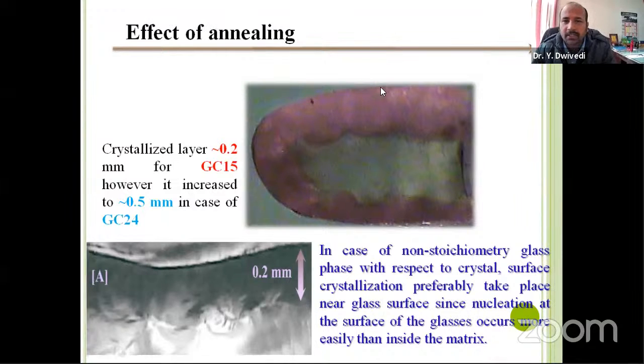You can see that due to some heterogeneity present near the surface and in the sample as well, crystallization starts from the surface and branches inside the system. So what happens is this unique structure forms: the upper layer is crystallized, you can see the pink scattered light, and here in between there is a transparent material.